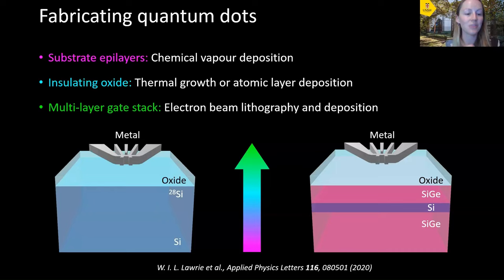And we need to use electron beam lithography to achieve these really fine features on the order of tens of nanometers. And the wavelength of light is simply not small enough to be able to pattern these features, which is why we need to switch to using the higher energy electron beams to pattern such small structures. And then after we do our metal deposition, each layer will be insulated from other layers in the gate stack simply by having a native oxide that grows when aluminium is exposed to air, or you can deposit a dielectric material in between layers using atomic layer deposition.